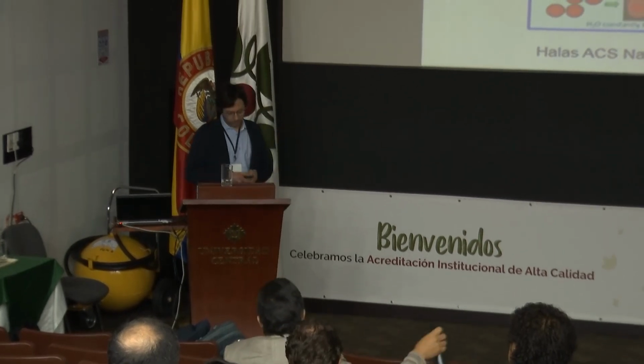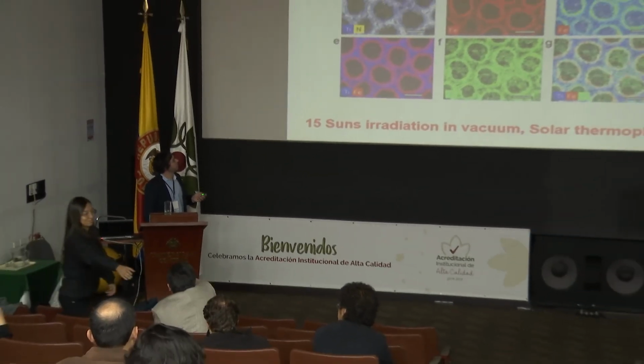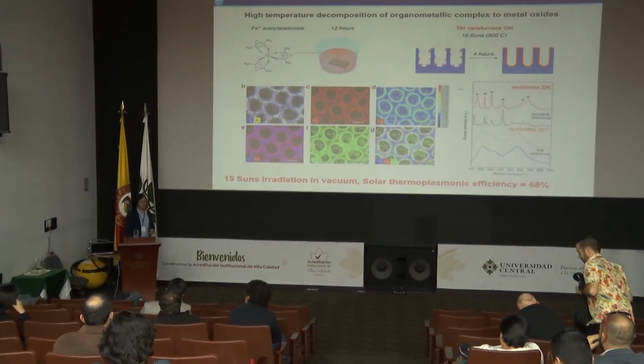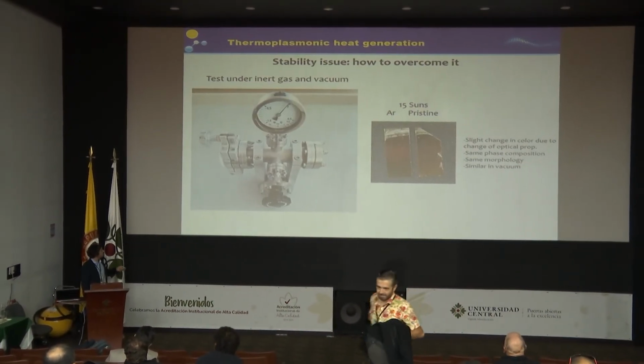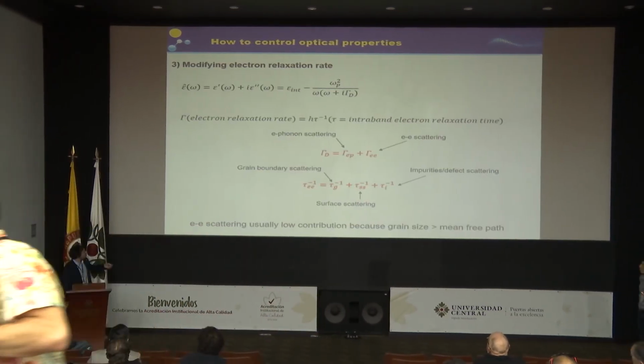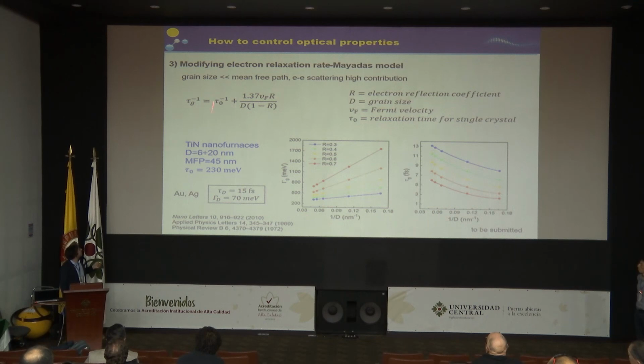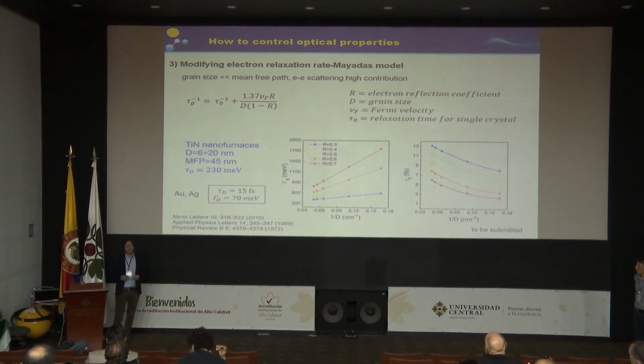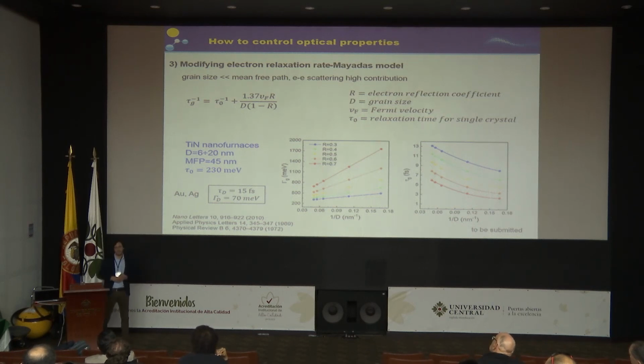Well, with a single crystal, you can really have nice quality resonances. While if you have polycrystalline, as you show here, we have lots of dissipation and a very high electron relaxation rate, because these grains are much smaller than the electron mean free path, and so you have lots of scattering events of the electrons which form your surface plasmon. So you can basically accelerate, if I can say that, the dissipation and the formation of heat or hot electrons.